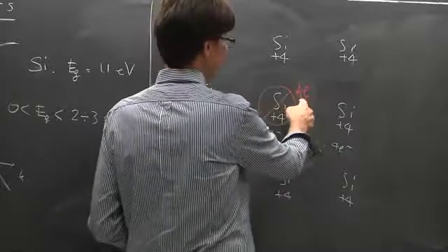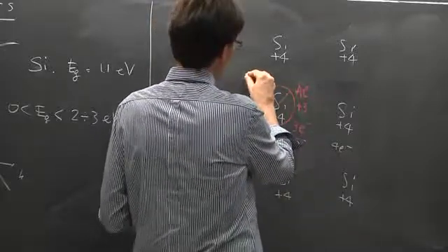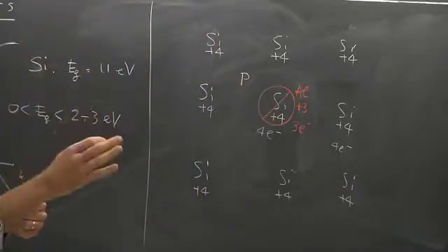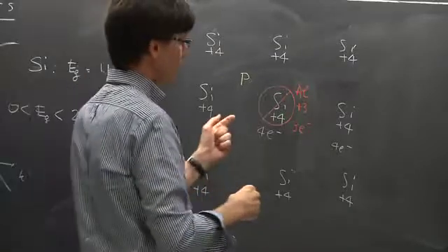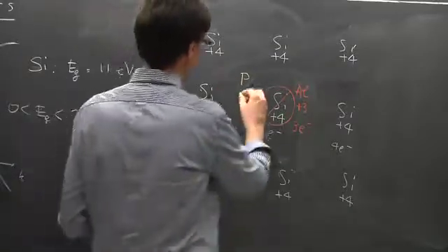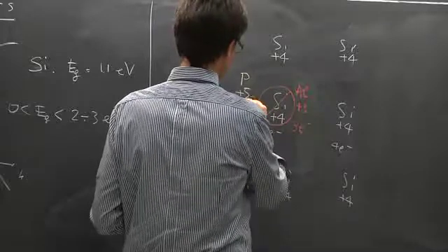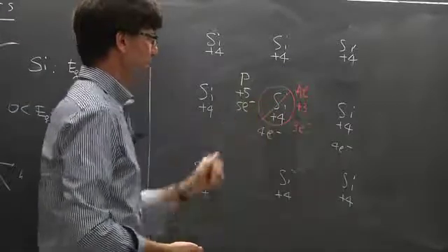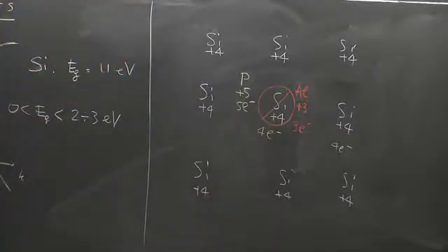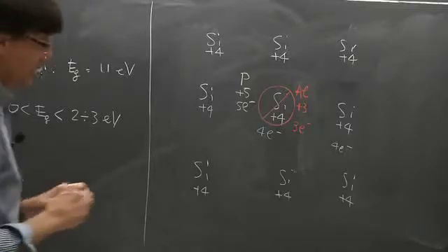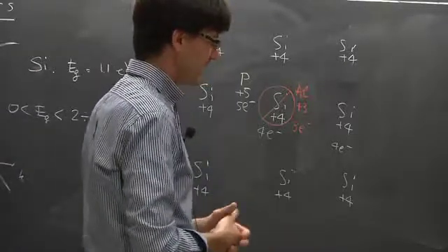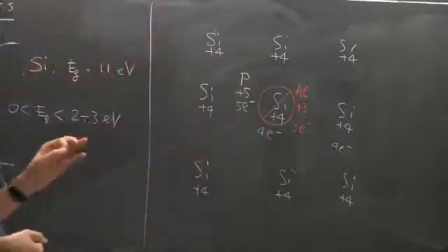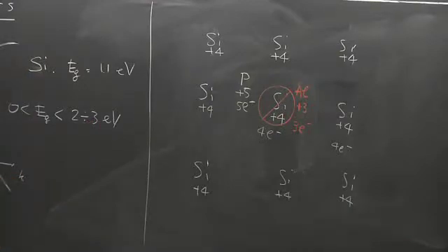Instead of replacing with aluminum, I replace it with, for example, phosphorus. Phosphorus sits on the right side of the periodic table, so it has one more electron and one more nuclear charge. So it's +5 and 5 electrons. The problem is very similar. It's actually symmetric. And again, I can throw little amounts of phosphorus in the reactor where my silicon crystal grows, and so I can have a small amount of phosphorus substituting silicon while the crystal is growing.